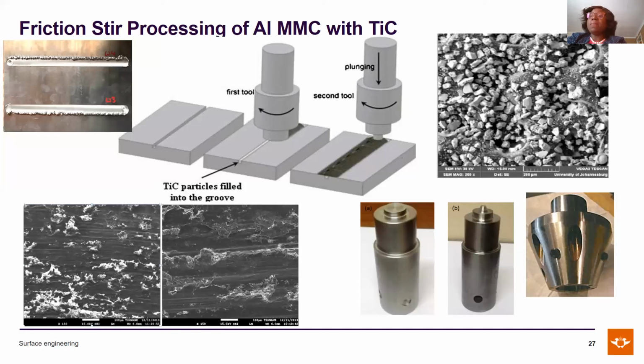We used titanium carbide powder, particle size of between 45 and 90 microns. We poured it into the groove, and first of all used a tool without a pin to consolidate the particles into the groove. That is what you have there as stage number 2. We use the tool on the right-hand side corner of my slide, designated as A, without a tool pin. We first of all run that tool with only the shoulder on top of the substrate, the parent material that we want to work on.